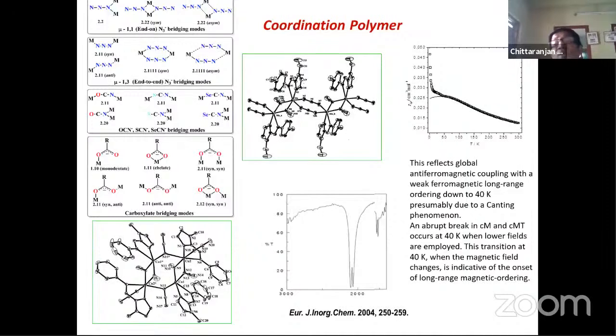These metal organic frameworks can change the behavior of the molecules with reference to their magnetic or thermal or photochemical, photophysical properties. You see one compound, that is a manganese compound, manganese 2 azide bridged. This azide can bridge in many ways with the metals. This is one type of bridging, this is another type of bridging, and so on. The azide bridging, acetate bridging, these are the common inorganic bridging agents. Manganese 2 is of d5 electronic configuration, having the highest magnetic moment in a single molecule system. And when it is in the polymeric phase, there are 5 unpaired electrons in this manganese, 5 unpaired electrons in this manganese, 5 unpaired electrons in this manganese, and it is continued for a 1D chain.